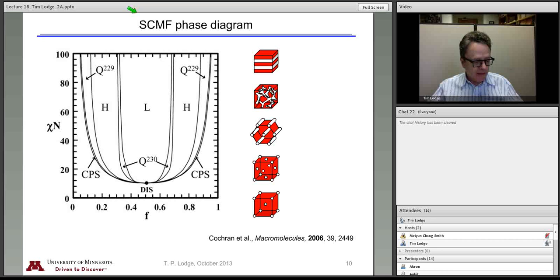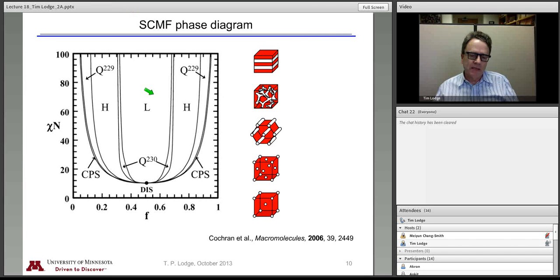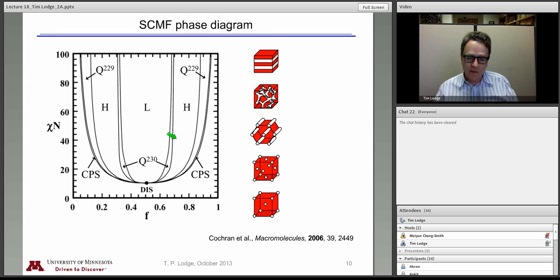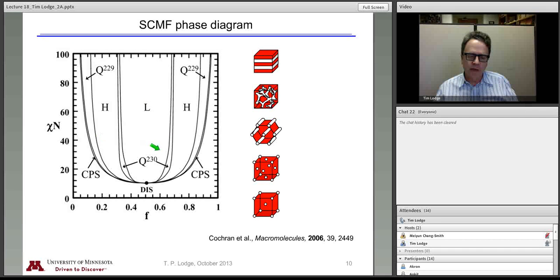What are we going to do with neutron scattering here? In general, neutron scattering is not the preferred technique to discover which ordered phase we have. Transmission electron microscopy is helpful, X-ray scattering is helpful, and in some cases rheology and birefringence are also helpful. Neutron scattering is probably not the best choice to decide which ordered phase we have. On the other hand, we can use it to ask some detailed questions. But out here in the disordered state, it is by far the most important technique — and again, this comes from the deuterium-hydrogen contrast advantages.